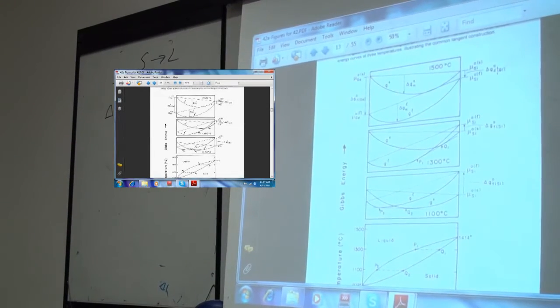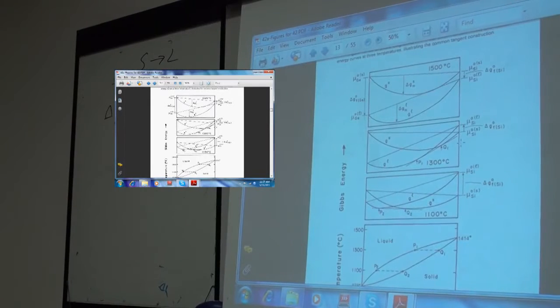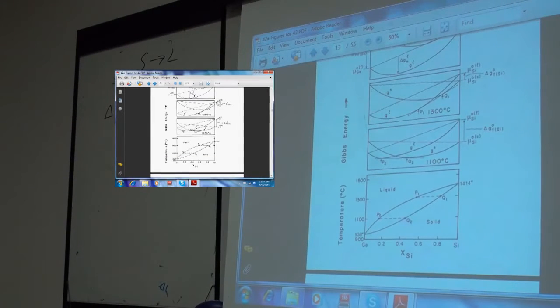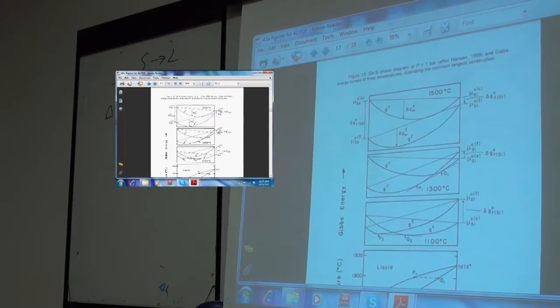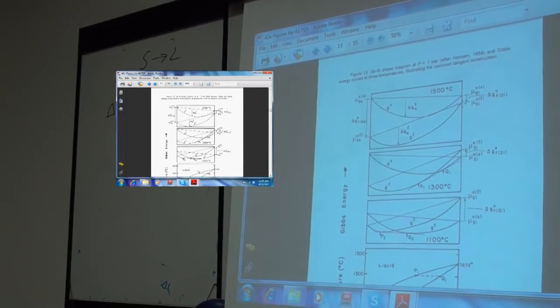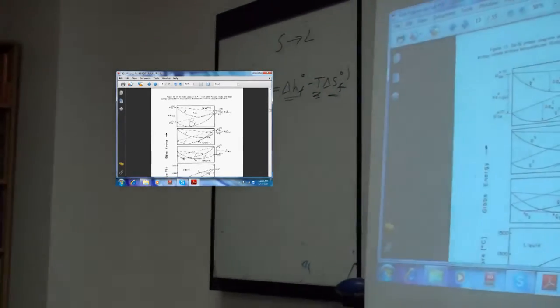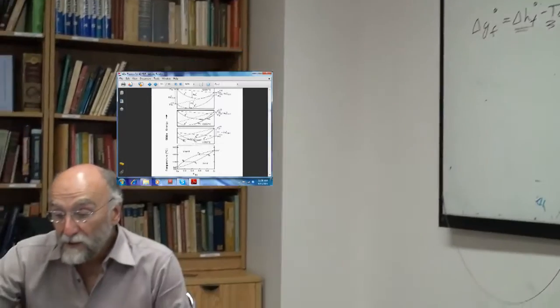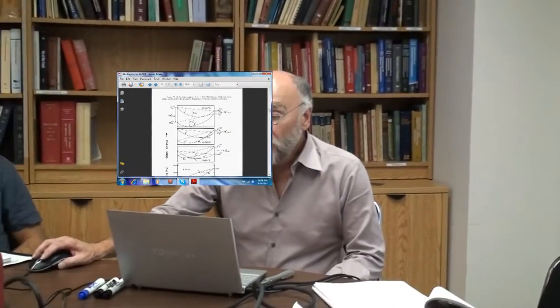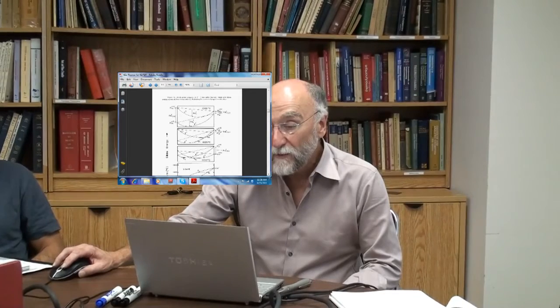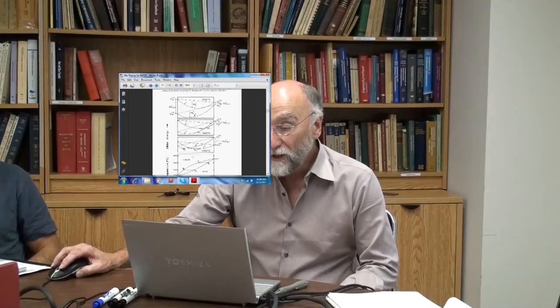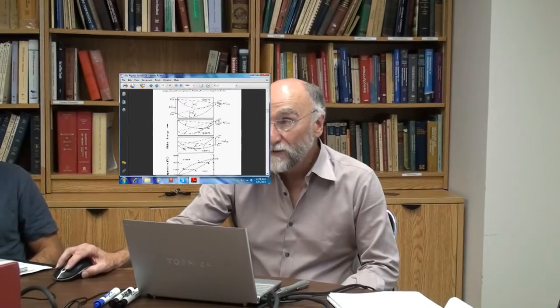If you reach exactly the temperature of 1414, which is the melting point of silicon, then you'll find that this point has moved down to exactly this point. If you move now down to 1300 degrees, which is here, then the two curves cross each other. This Gibbs energy of fusion now is positive, the Gibbs energy of fusion over here is negative, so at 1300, pure silicon is solid, pure germanium is liquid. The two curves cross,